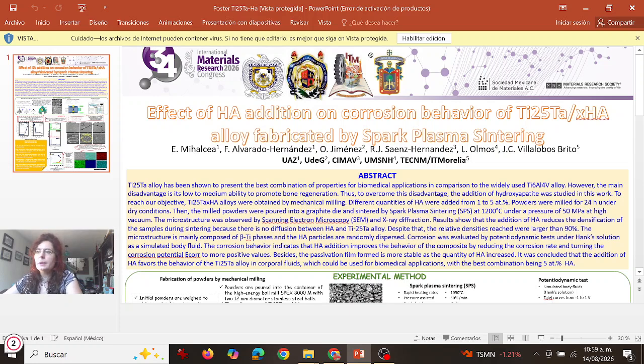So it was concluded that the addition of the hydroxyapatite favors the behavior of the titanium 25 tantalum alloy in the body fluids, and this could be used for biomedical applications. This is our interest. That's why we tested it in the body fluids. And the best combination seems to be the 5% atomic percent of hydroxyapatite added to this alloy. All right, very good. Now you have an idea of what this poster is all about.